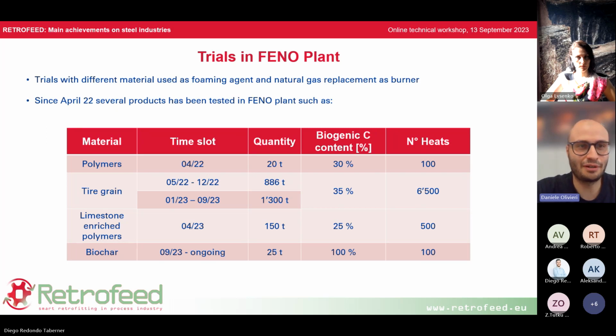And finally, our ultimate aim is to try biochar. The trials are still ongoing. We have tried a few tons so far. We will see how many tons we are going to try, but the main advantage of this material is that it contains almost 100% biogenic content. It is all derived from biomass, which has been treated at high temperature with low oxygen, of course. And we're still ongoing with this material. We can go on.